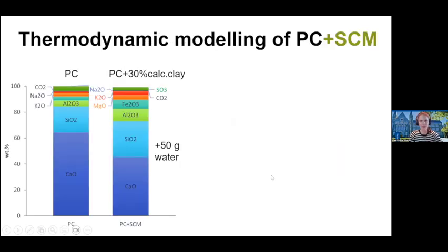But when we've done that, and here I did it for, so on the left, we have the figure for pure Portland cement. And on the right, I have replaced 30% of the Portland cement with calcined clay. And you can see that that changes the oxide composition of your total cement. So you have less calcium oxide, more silicon oxide, aluminum oxide, and iron oxide. And again, I let it react with 50 grams of water.